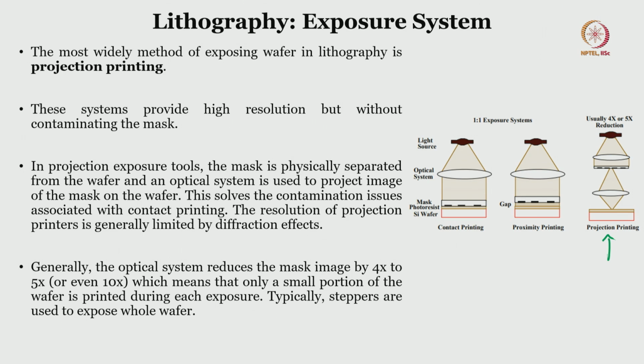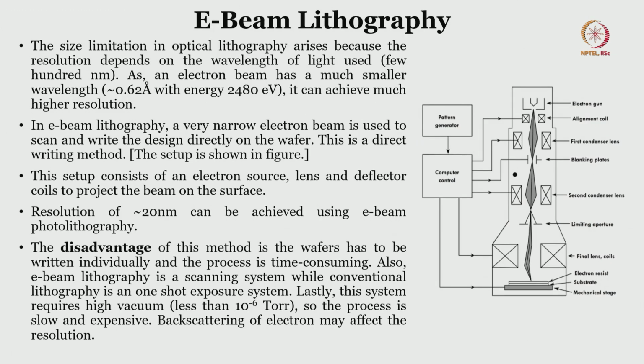The resolution of projection printers is generally limited by diffraction effects. Generally, the optical system reduces the mask image by 4 to 5x, which means that only a small portion of the wafer is printed during each exposure. That means typically steppers are used to expose the whole wafer. Since you are reducing by 4x to 5x, only part of the wafer is exposed, as you can see here. If you want to cover the entire wafer, then you have to go for stepper motors, which are generally used to scan the entire substrate. So, now we have seen UV lithography.